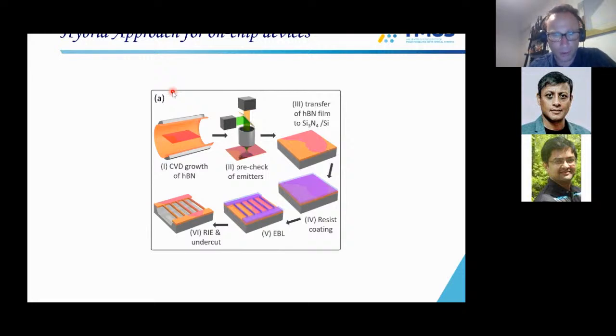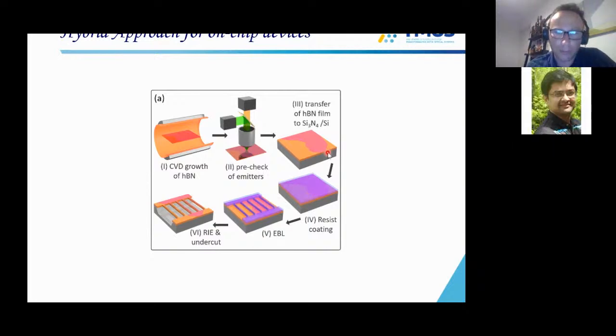Okay, so of course, because we're working with a layered material, we can take advantage of fabrication of other systems. We can fabricate cavities from silicon nitride, for example, and then pattern your hBN, transfer it onto silicon nitride, and then etch down the system together with the hBN. This works quite well.